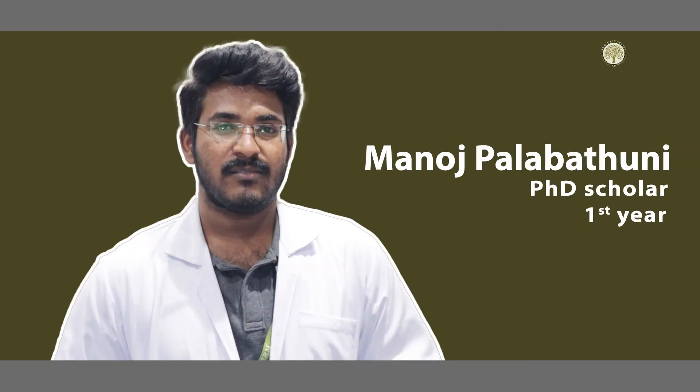I am Manoj Palabathuni, first year PhD student. From the literature, conventional amine-based perovskite nanocrystals often suffer from instability in ambient conditions due to their highly reactive surface. The resulting amine-free perovskite nanocrystals are more stable both in colloidal solution and in thin films. Even more, amine-free perovskite nanocrystals are more stable in harsh conditions like UV radiation, methanol treatment, and water treatment. All this together makes amine-free perovskite nanocrystals suitable for realistic optoelectronic applications.